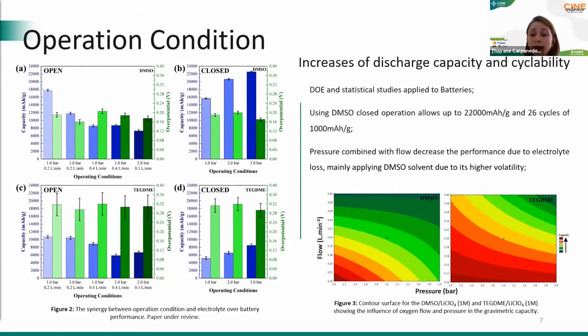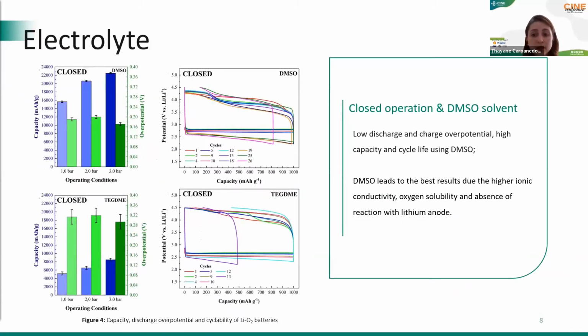In addition, the pressure combined with flow, studied by DoE, showed that the flow in the open system combined with the pressure decreased the performance due to electrolyte loss, and it was verified mainly for the DMSO solvent due to its higher volatility. So this analysis also points out the higher performance when using DMSO as solvent, with a lower overpotential and also a higher discharge capacity and cyclability.